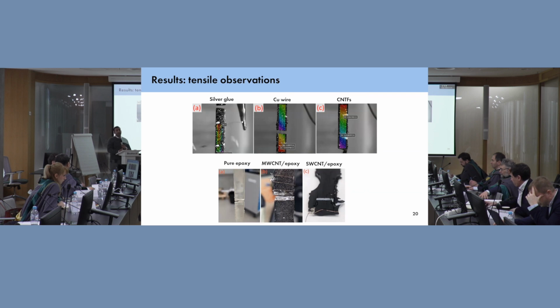But one of the most interesting findings was that during our tensile mechanical testing, we noticed that wherever we had samples with embedded metallic electrodes, we had failure at the site of the electrode, along the electrode. So wherever we had silver glue attached for making our contacts, as soon as the sample would fail, there would be a little shock force and they would detach. So this goes into saying that if you're going to use such contacts, there are problems with it.